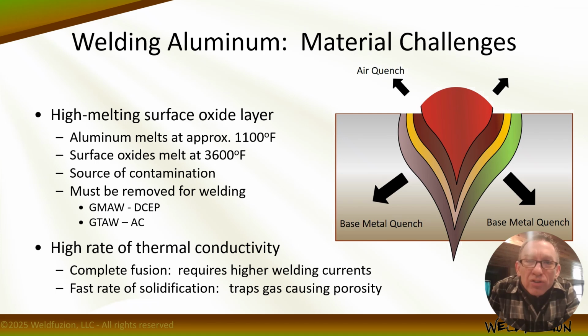You can also see some cleaning electrically using DC electrode positive and argon shielding gas, which etches the oxide layer around the weld area. This is perfect for gas metal arc welding that uses predominantly DC electrode positive for wire feed applications. But that would eat your tungsten if you're TIG welding with DC electrode positive. So instead, with TIG, we use AC or alternating current to get cleaning as the current switches back and forth between negative and positive.